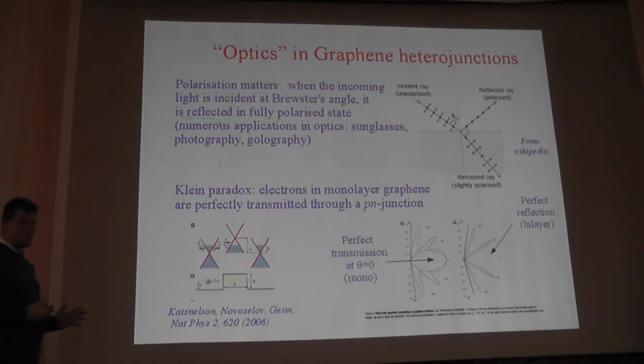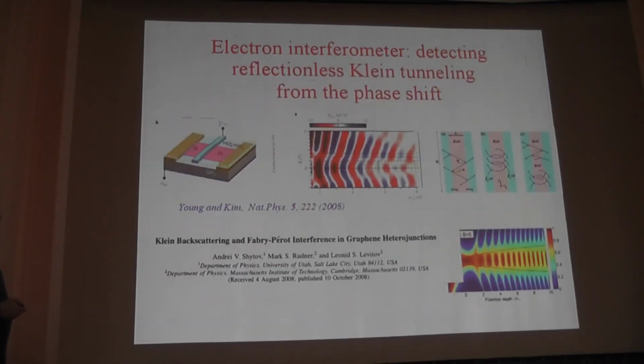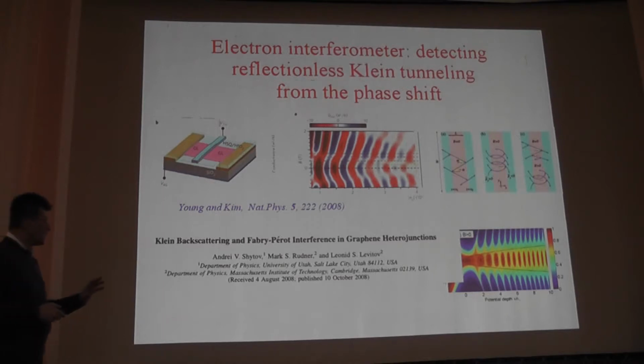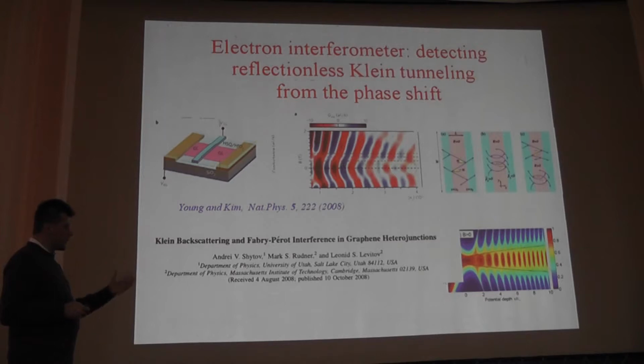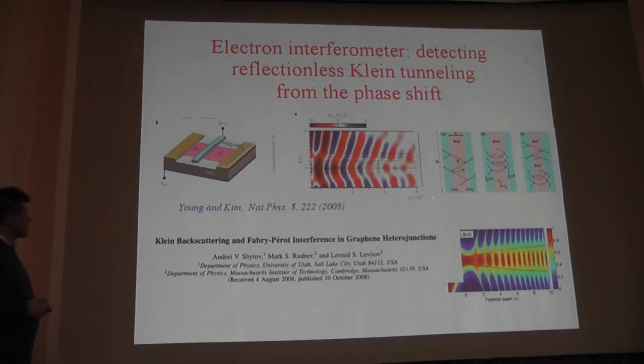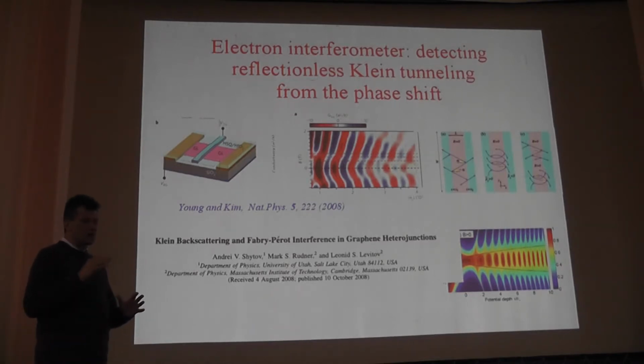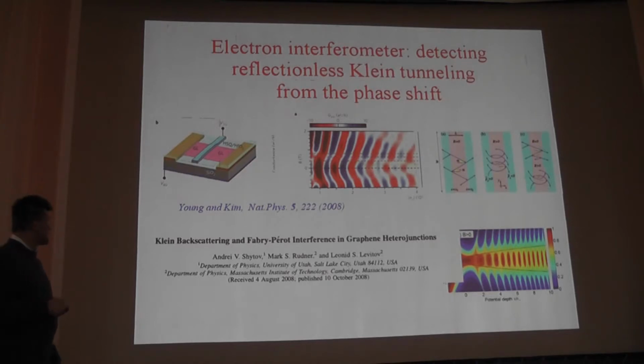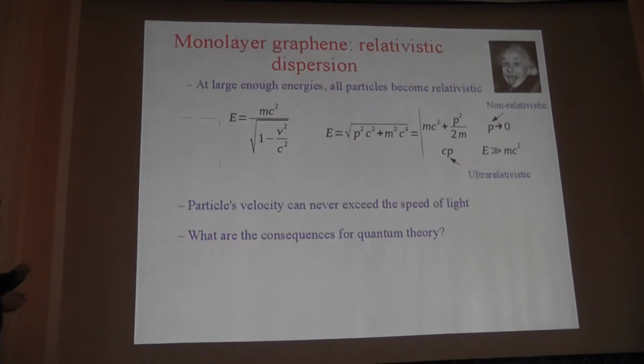But in fact, it's possible to detect Klein tunneling if you apply a magnetic field, if you curve electron trajectories, if you can control incidence angles with the magnetic field, then you can spot the point where the reflection coefficient is 0. When the reflection coefficient passes through 0, it changes the phase. And this phase affects quantum interference in this structure. So this way you can notice a shift in the quantum interference pattern, and it was in fact possible to notice this phase shift in a real experiment, and that's one of the pieces of evidence for the Klein paradox.